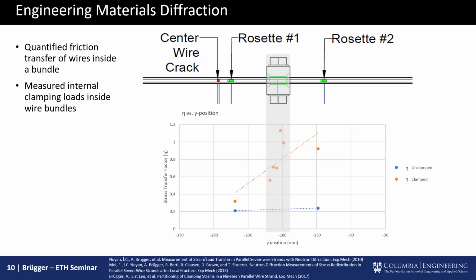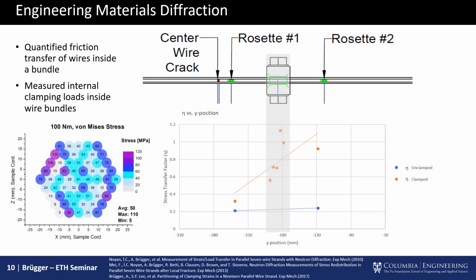But of course, that begged the question, what does this mean in real life? What is my confinement in a real cable? Can I assume a mean field distribution throughout this contact regime? And that's actually a much more difficult question than we thought, because when we measured it, this is some of the final results from some work a couple of years ago. You can see that we are now looking at the confinement forces, the forces in this plane, essentially the compression forces on the specific wires, the 61 wire strand, and you can see that it's a relatively chaotic system. We have certain wires that are under heavy compression. In this case, these are von Mises stresses. Other wires that are almost unstressed.